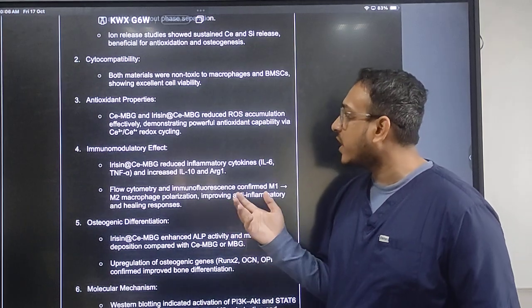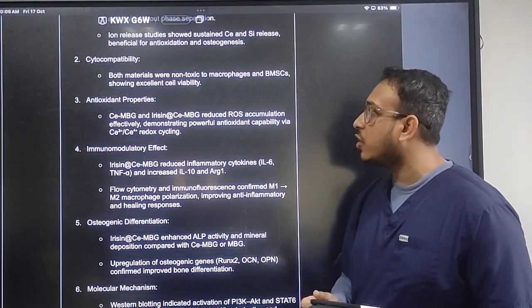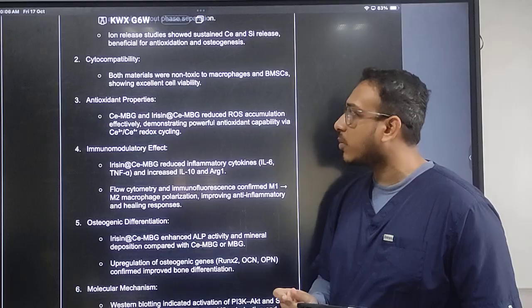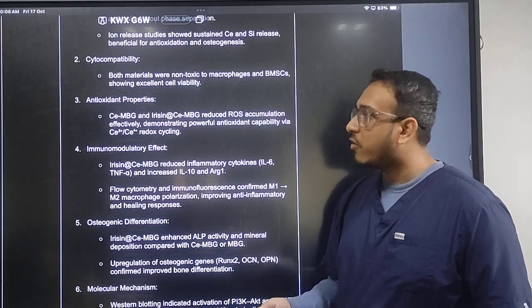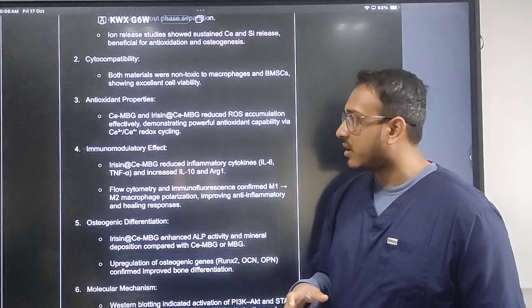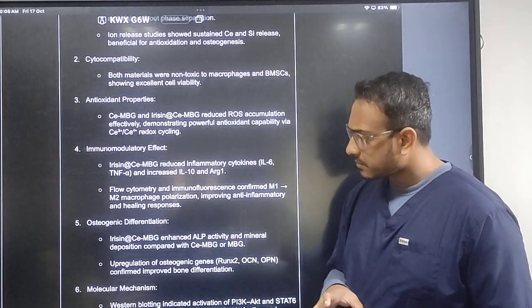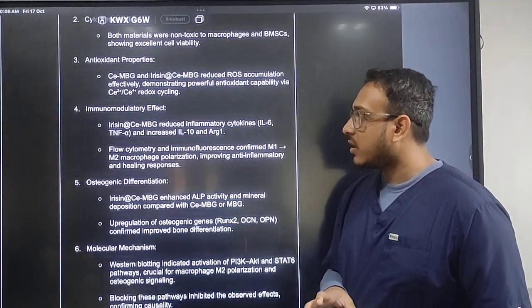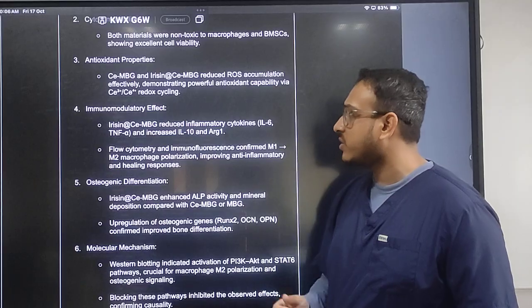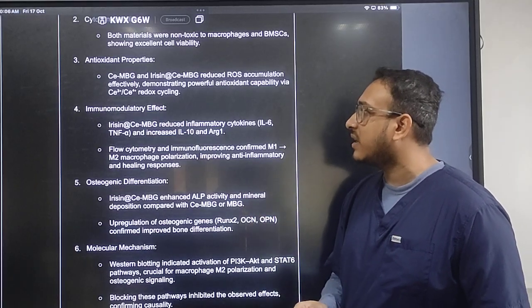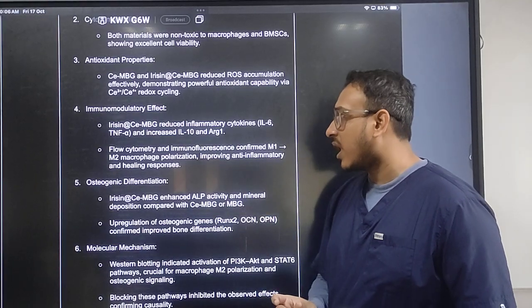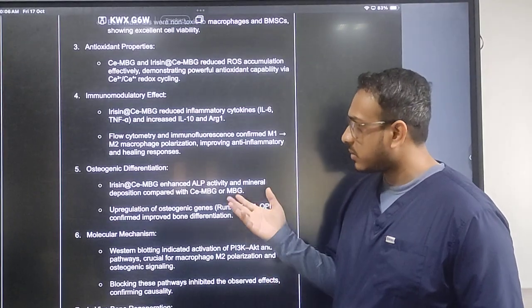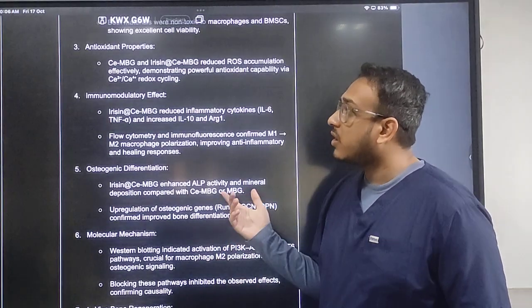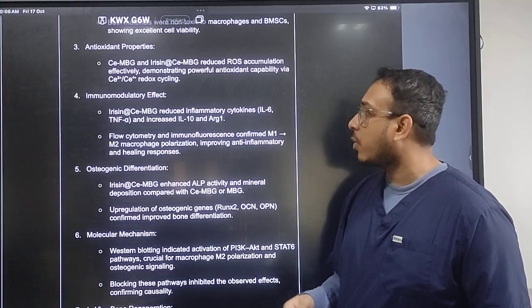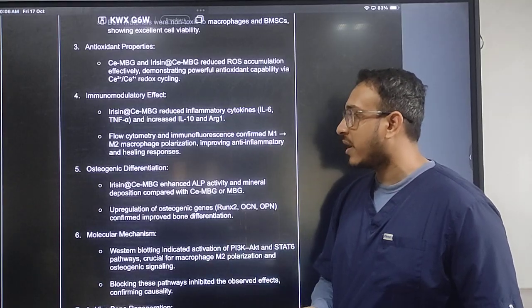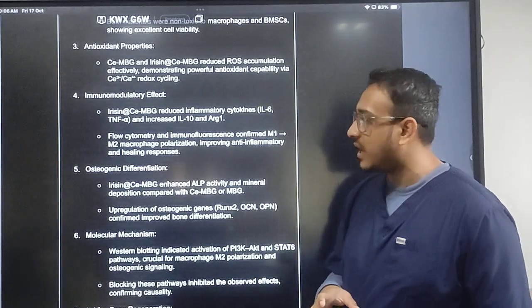The antioxidant properties: the material reduced the reactive oxygen species accumulation effectively, demonstrating powerful antioxidant activities via cerium redox cycling. The immunomodulatory effect: the material shows reduced inflammatory cytokines and increased IL-10 and Arginase-1 cytokines. The flow cytometry and immunofluorescence confirmed the M1 to M2 macrophage polarization, improving anti-inflammatory and healing responses.